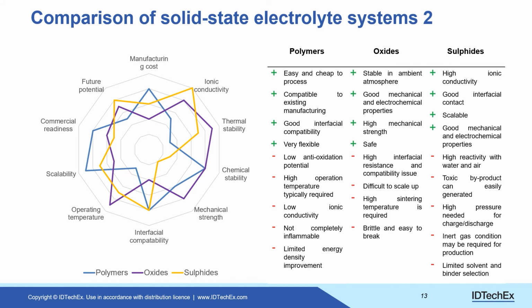So in general, polymer-based electrolytes are easier to make and fabricate, and they are also the closest to commercialization, because there are already some vehicles equipped with polymer-based electrolyte. But they have a low antioxidation potential, higher operating temperature, lower ionic conductivity, etc. For oxide, usually there is really good chemical stability, but the higher sintering temperature makes manufacturing more difficult, not to say the higher interfacial resistance.